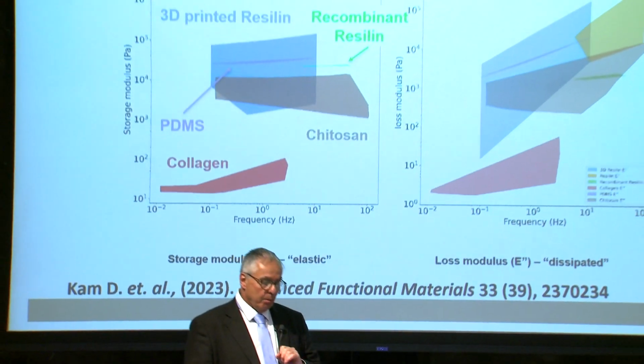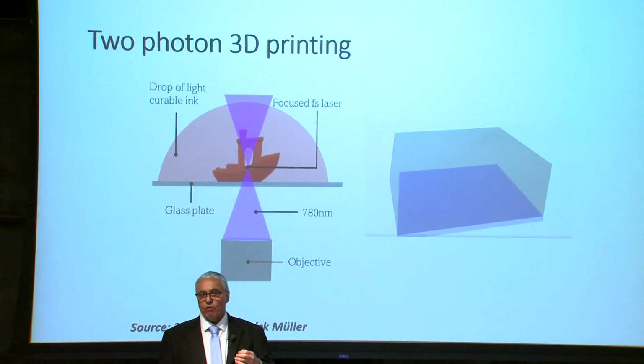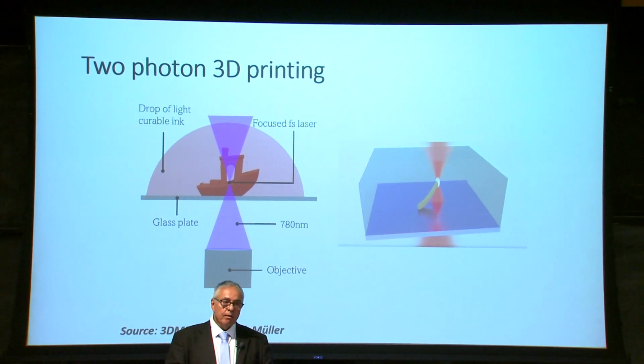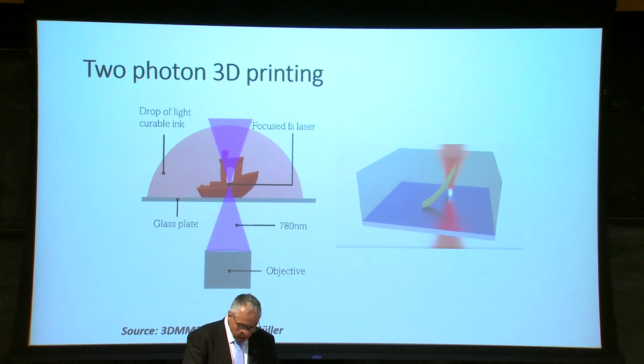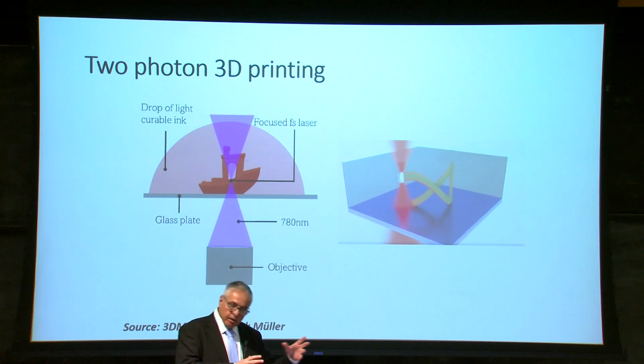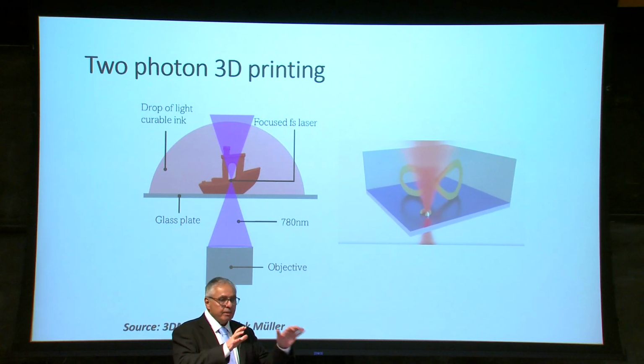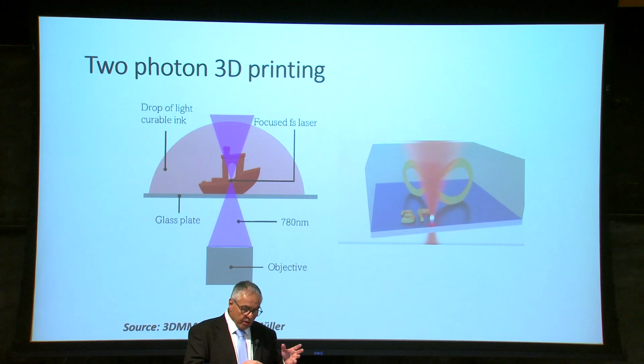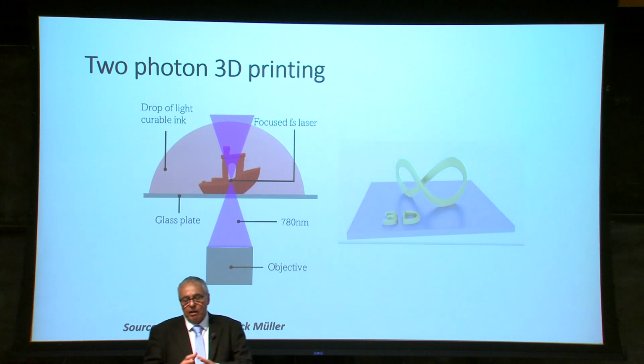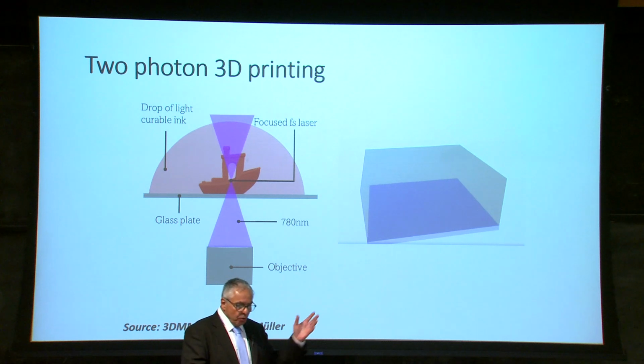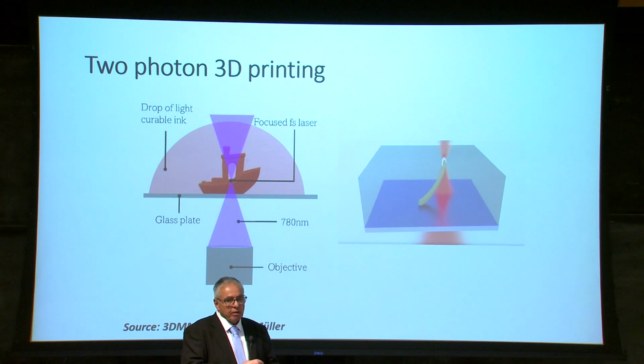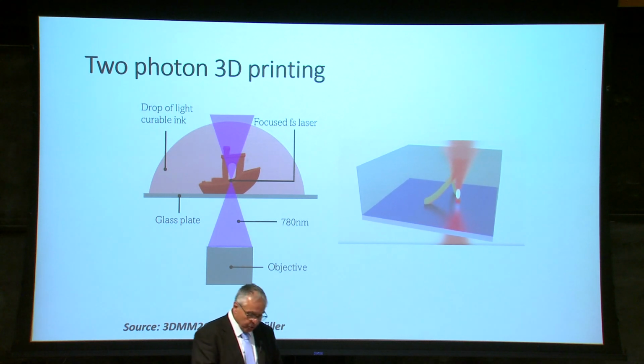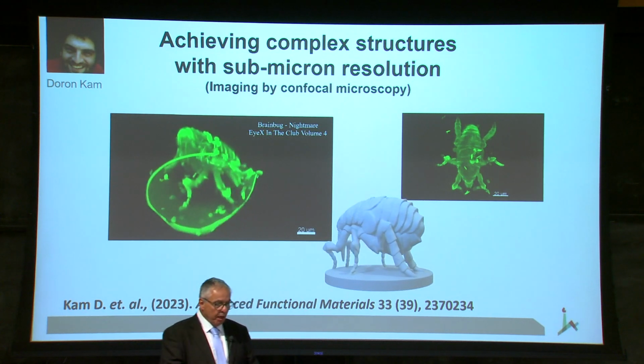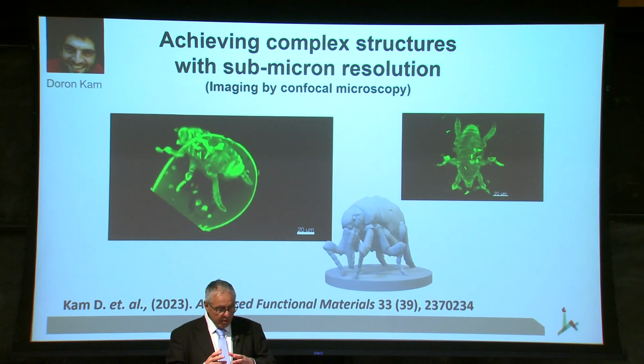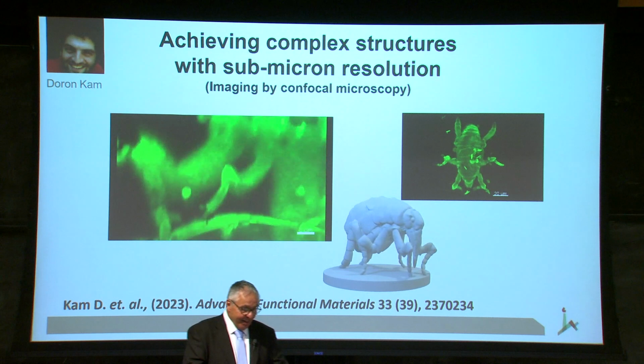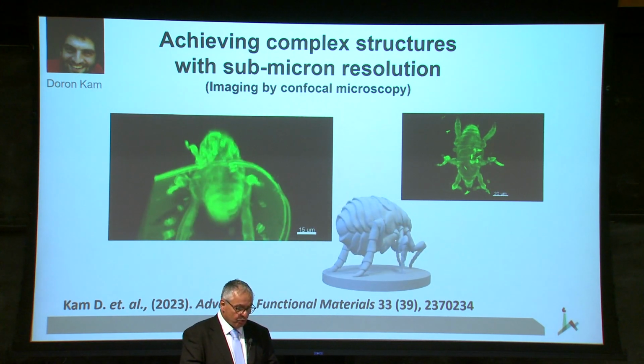But interestingly enough about the resilin is that, in fact, it's a photopolymer. In nature, actually, the material is being cross-linked using an enzyme, which actually forms the dityrosine bridges. But we were able to take this protein, just adding a photoinitiator and using a Nanoscribe, which is a two-photon printer that enables us to print submicron structures. And by doing that, Doron was able to print a resilin-made insect, and you can see here it's a sub-micron resolution.